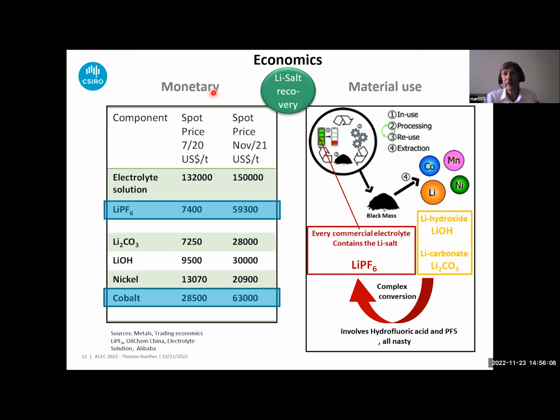Looking at the monetary aspect, we see from this table of the spot prices that the LiPF6 price has increased significantly from mid-2020 to the end of 2021. It's sitting around $60,000 per ton, which is quite similar to cobalt, which is chased in most processes.